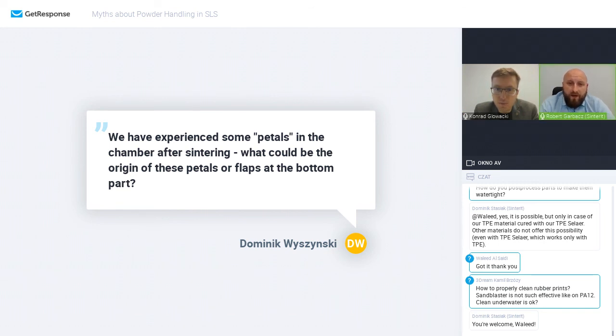Well, when we start sintering powder in our machine, we need to create some sort of safe environment for starting the print, and we heat up the chamber pretty fast. So if you're sintering layer by layer, when you're penetrating it with the laser, you're not penetrating only one layer, you're penetrating like 3 or 4 of those layers, even more. That's why when you're starting the print, there are some petals at the bottom, but you should minimize it when you position everything at 45 degrees.